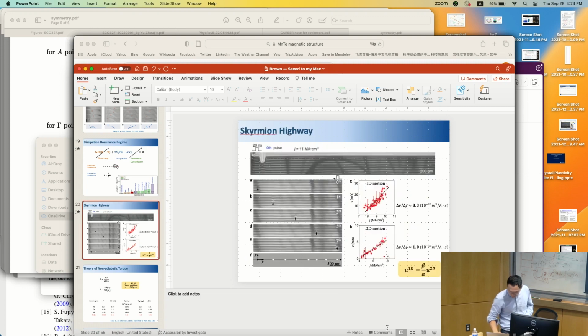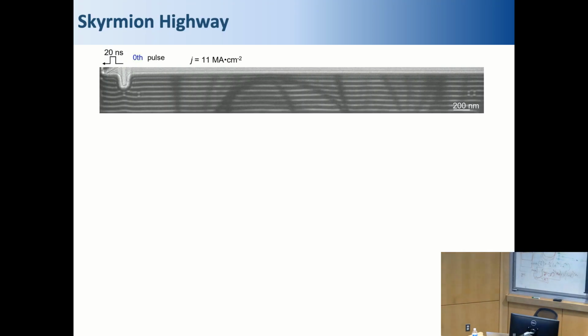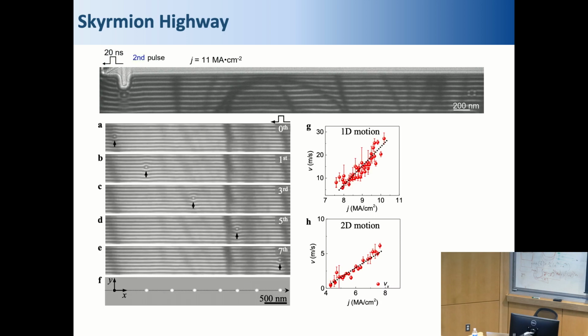Any other questions? There seem to be different intercepts between 2D and 1D. Is there any information to be extracted there? There's an intercept that's non-zero for the 2D. Yes. So in 2D, the skyrmion starts moving at low current. But once it's confined in 1D, although the velocity is higher, there is a problem because the skyrmion can be easily pinned by local impurity. You need a little bit larger current to drive the motion of the skyrmion. But once it starts to move, it moves quickly. So this is the point.